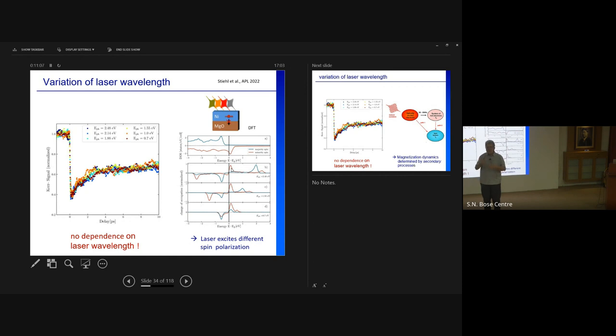We discussed that this morning. When you excite one electron, you do not change just a spin-up electron. At that moment, you do not change magnetization. You still have the same amount of spin up and spin down. You have to flip the spin. You have to transfer angular momentum away. That's not possible optically. But if there is a transport of majority and minority spin into two different regions, then yes. But that's not something we discussed this morning. When you transport one spin component out of the probed system, I agree, then yes. But it's a secondary process. It's not a primary process: optically, even with circularly polarized light, you cannot create a spin ferromagnet. Okay, thank you.